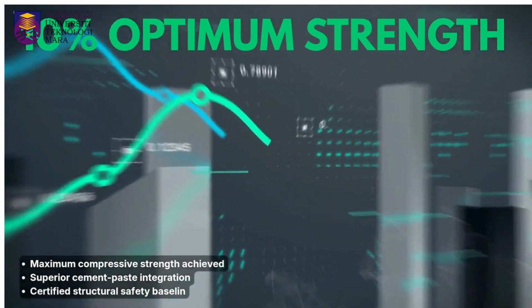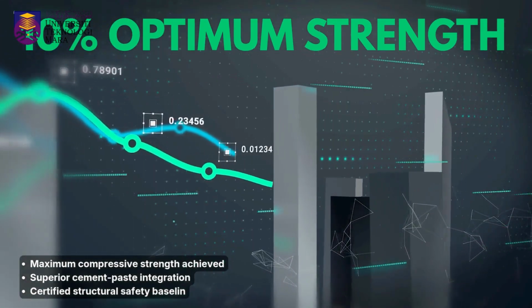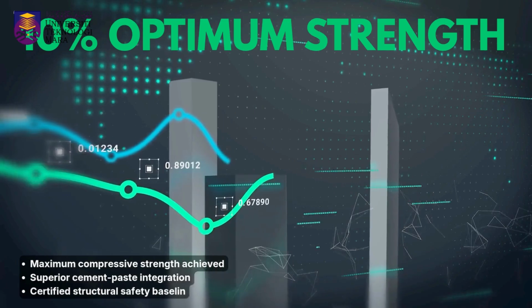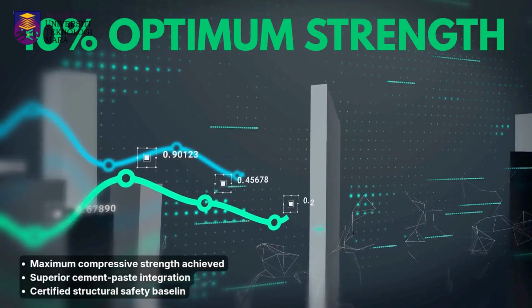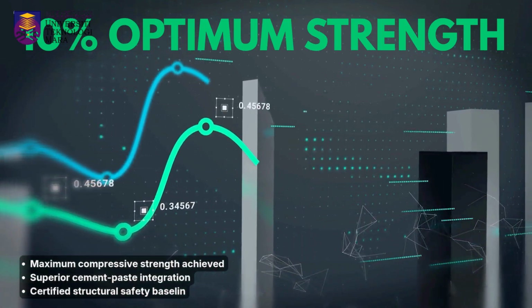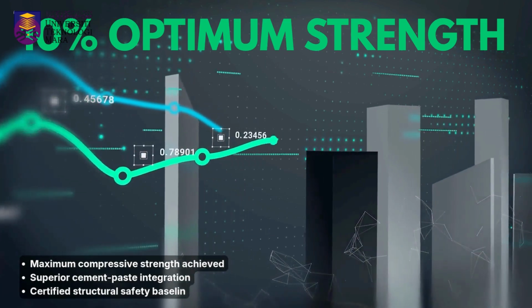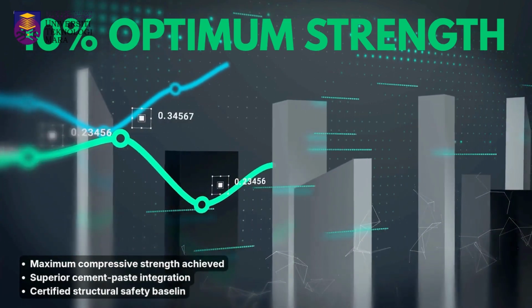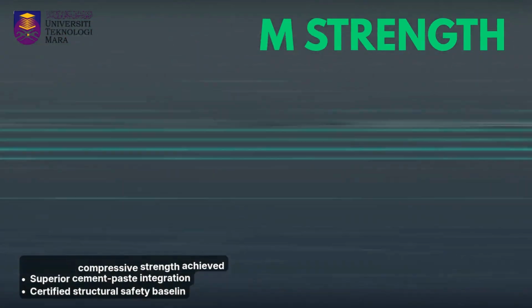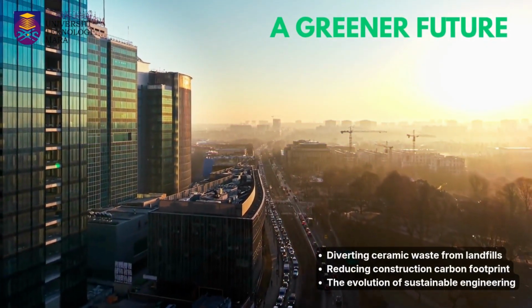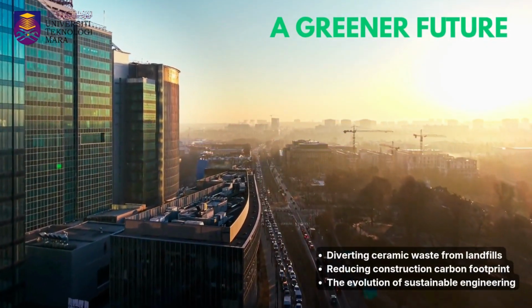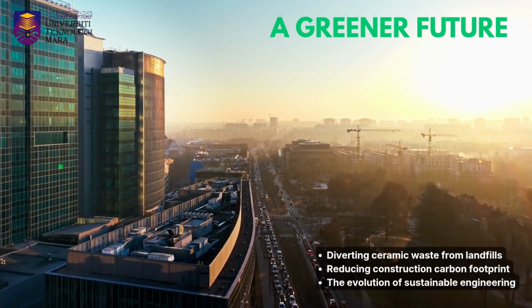Among all our tested samples, it was the 10% replacement level that achieved the most superior compressive strength performance. At this precise percentage, the recycled tiles integrate perfectly with the cement paste, maintaining structural safety while maximizing sustainability. Ultimately, this study is about more than just concrete cubes. It's about a paradigm shift in how we approach civil engineering.